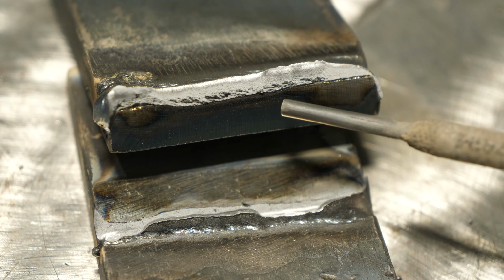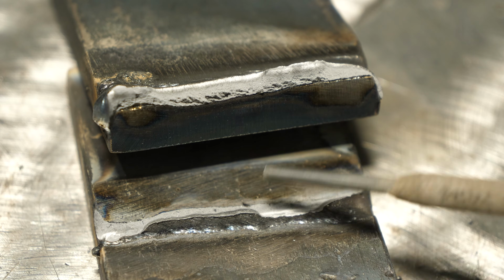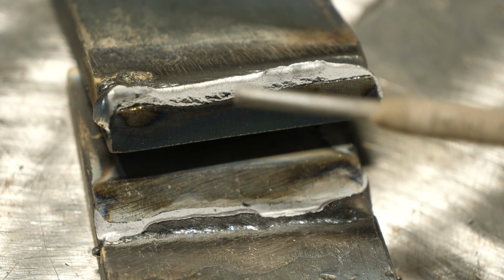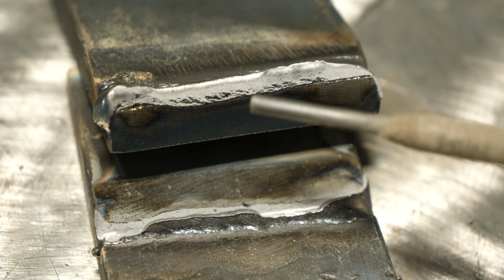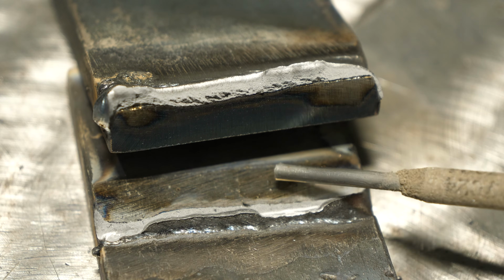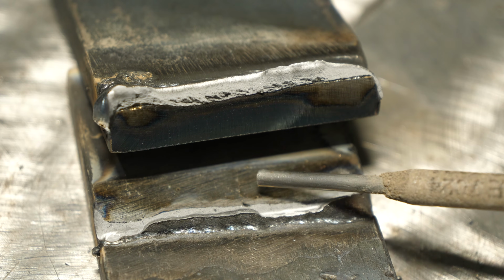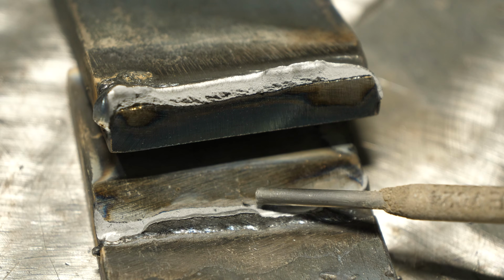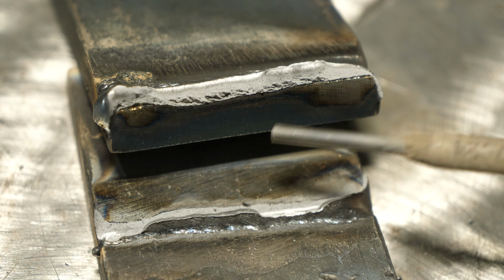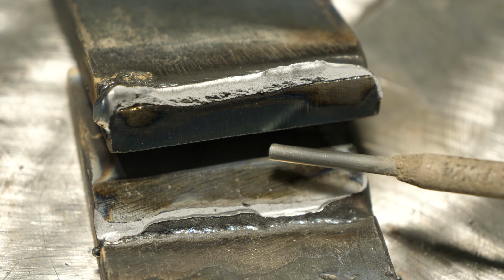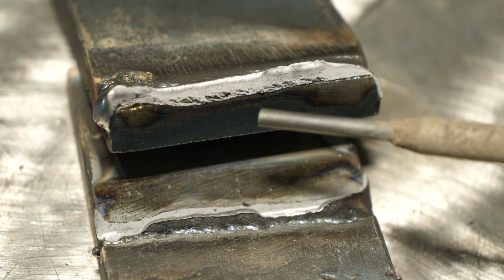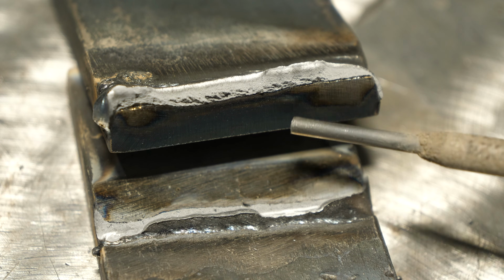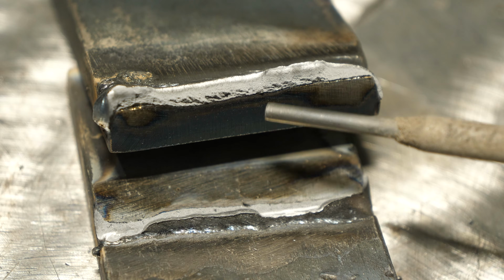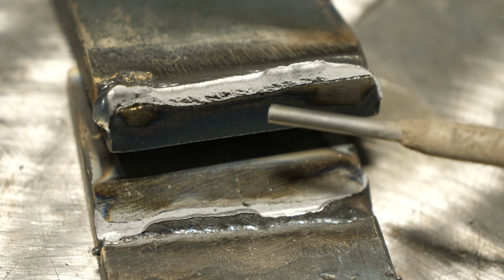This really doesn't look that much different than 70-18, and not really a whole lot different from, I guess, 70-14. Now, the test results put it right at the low end, maybe a little bit under what 70-18 would normally perform in this test with my test equipment. So it's not as strong. I had made a prediction. I thought it was going to be up in the 90, maybe 100, and it wasn't.